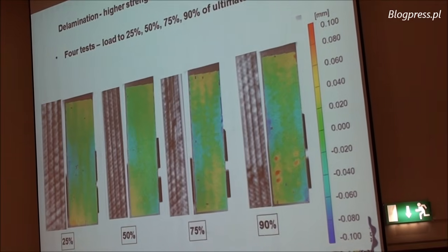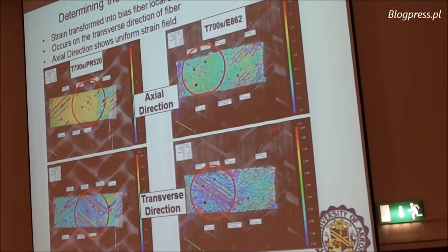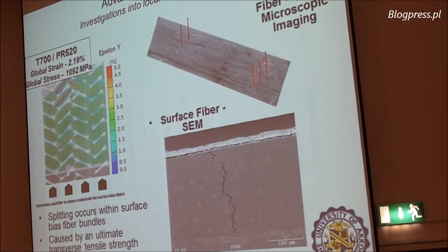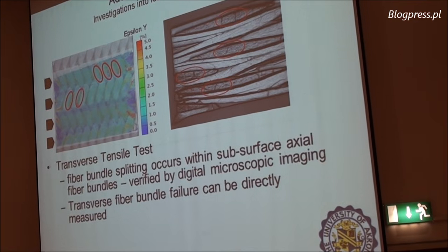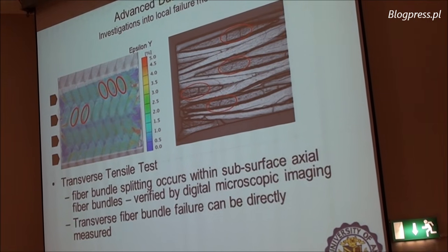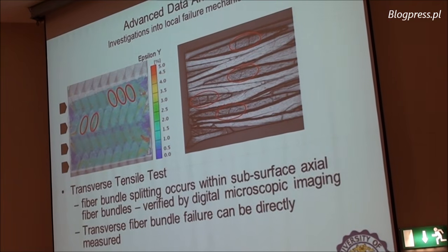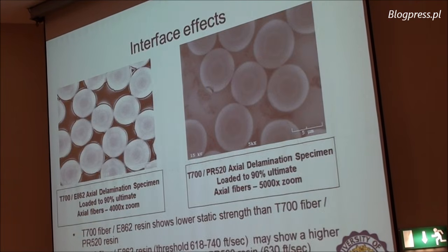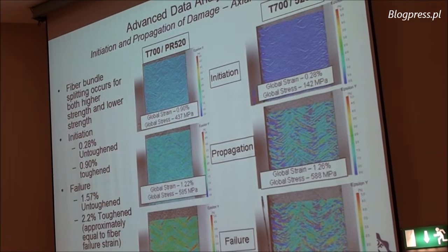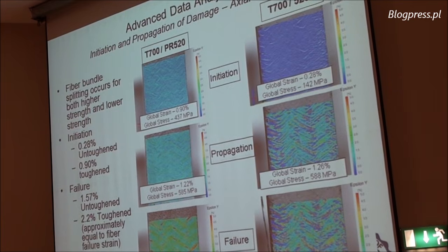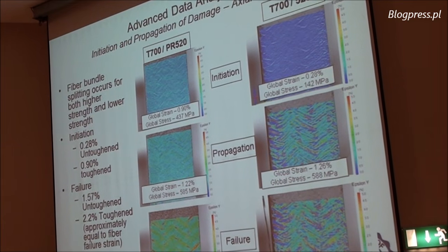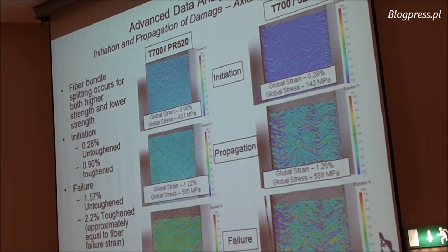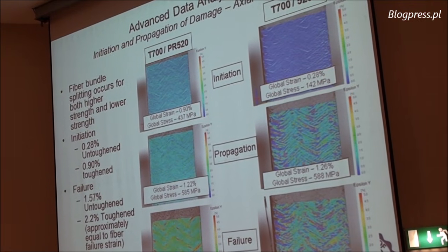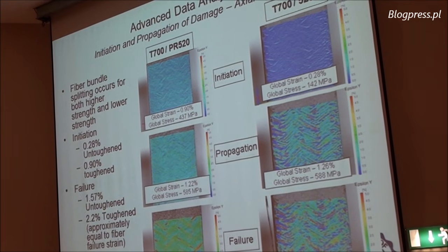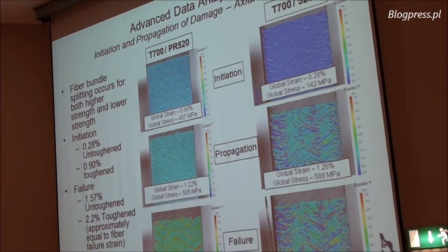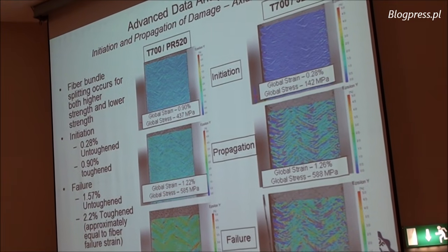So we spent a number of years to understand the different failure modes. We found through the thickness the splitting of the bundle that are shown circled, and we looked at the microscope, we looked at the bonding at the fiber level, and we found that even for the same fiber, but two different resins, which globally give almost similar behavior, the local stress-strain can reproduce different damage progression or behavior of the material itself.